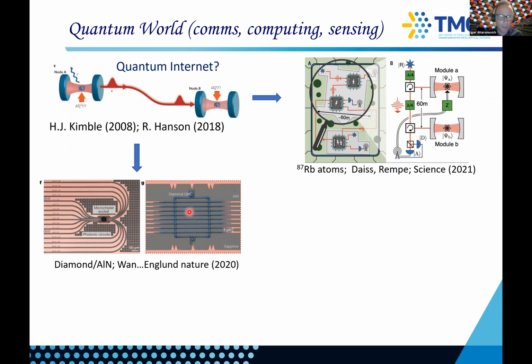So they chose a hybrid approach where they're using diamond as the hardware building block and aluminum nitride as the information carrier to interface with photons. And so here they managed to basically integrate about 16 nearly transform-limited solid state spins that were based on germanium vacancy in diamond. There was no indistinguishability yet, but that's on the way to go. So this is a hybrid approach.